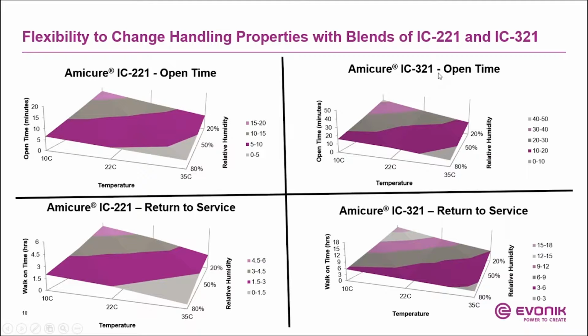As I mentioned before, this can also be IC-321, because they have the same reactivity. So they have slower reactivity. As you look at regular conditions, you're in this dark purple here, you have about 20 minutes working time, and get back on it around 6 hours. But the benefit here is that you still get enough working time as you go to higher humidity, higher temperature. So that's the benefit with 321, while still getting fast return to service.